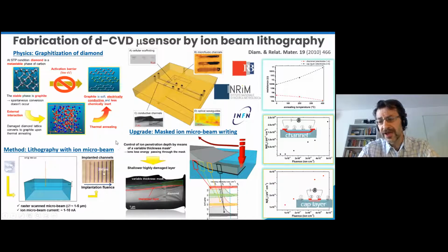At the bottom of the picture, you can see the vacancy profile. By implanting through a mask, we can create these conductive channels from the surface through the bulk of the diamond to the central position where we can place a neuron cell, for example. By applying electrical current, we can stimulate the cells. Also, by ion implantation, you introduce strain in the diamond lattice, so you can change the refractive index. So you can also use these channels as waveguides for optical stimulation of the cells.